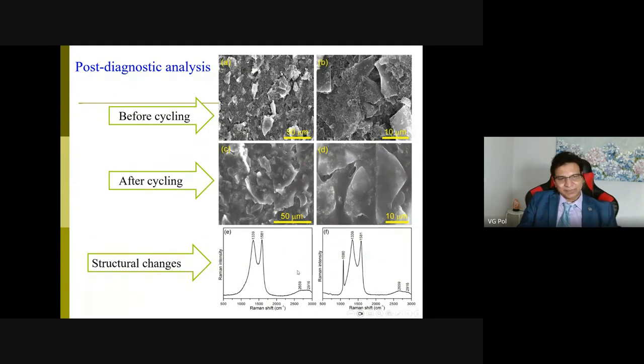And then we again did the structural analysis, which has an additional signal here that belongs to lithium carbonate. That is the byproduct of decomposition of electrolyte that forms inside the battery during the charge and discharge. However, the carbon sheets remain carbon sheets while cycling, or charging and discharging, the battery. So long story short, we made one material sustainably that acted as the anode material for batteries, and batteries were very good.